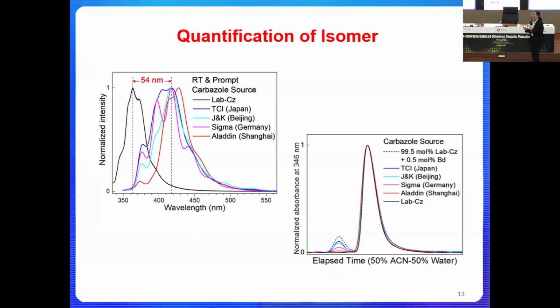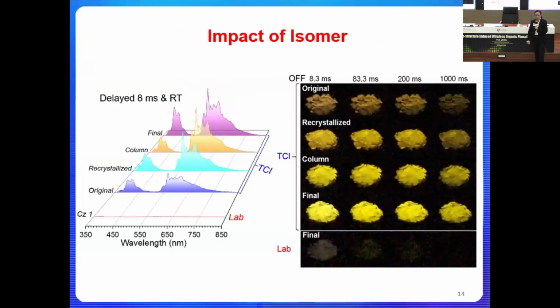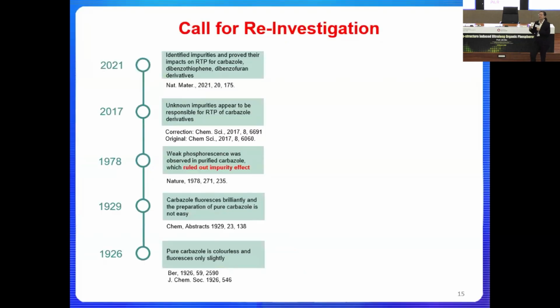So that is why, if we rely on NMR to check the purity of the compound, we're not able to detect this small amount of impurities. And that is the reason that for so many years, people were working on this compound, but no one was able to discover that there's this small amount of impurity that is making a huge difference. And this impurity is very difficult to separate. If we use traditional column recrystallization, we will not be able to easily get rid of this impurity, but instead we can get rid of other impurities, so that the doping effect becomes much more obvious. That explains why there are so many groups working on this compound, but nobody was able to discover that there's this tiny impurity that is the real reason to explain this property.